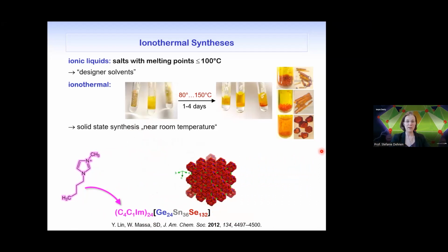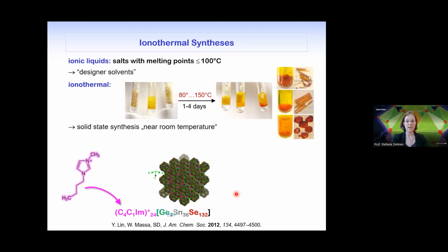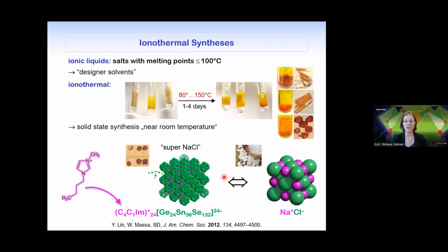And just to have a preview of this crystal structure, you can see that everything that is anionic, a very complicated formula though, is drawn in green here. So these ball-type anions, and we have the pink cations in between. And if you analyze the structure of this compound, you will find that it's generally isostructural to sodium chloride. So very complicated and larger in scale, but the overall symmetry is like in sodium chloride. And you see that the color is different, so you would maybe call it a super sodium chloride, but you would probably not taste it because the elements will not be very healthy, so better don't.